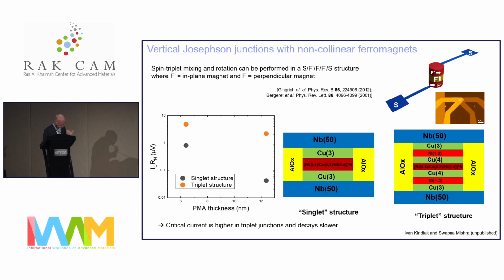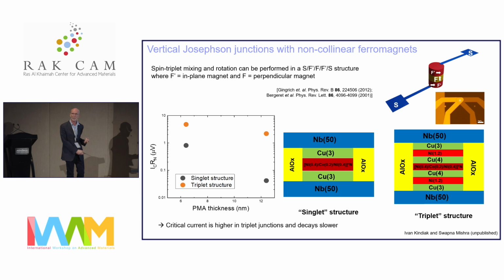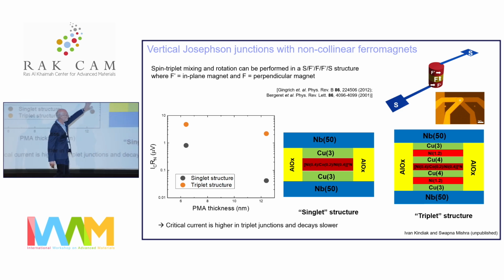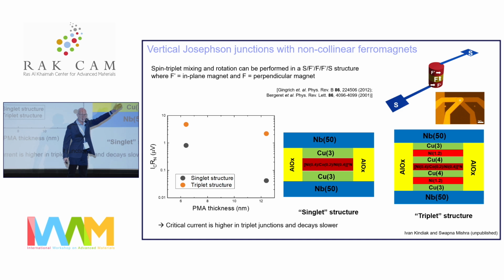Now, what Sébastien Bergeret showed 20 years ago was, okay, actually, if you introduce, let's say from niobium, we have a spacer layer, here is a ferromagnet, it's actually formed from the same materials we form our racetrack, cobalt, nickel layers, each one individually a few angstroms thick. The broken interfaces give rise to a perpendicular magnetic anisotropy. The magnetization is pointing up.